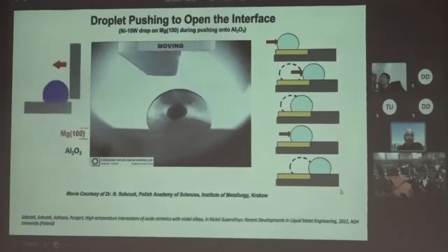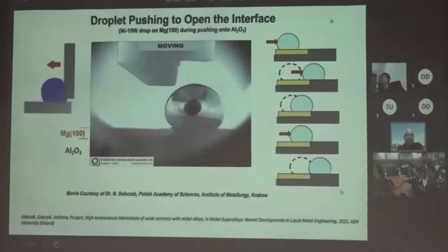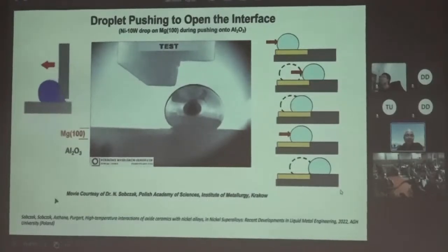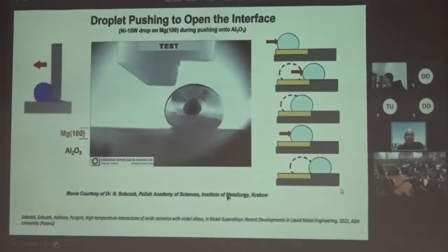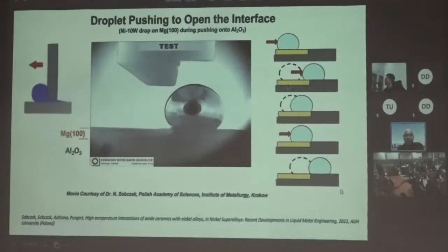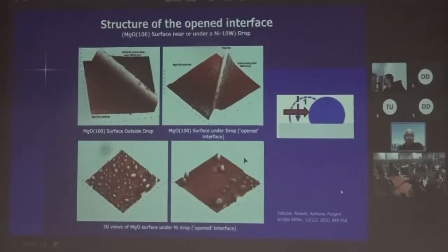One of the things we have been able to do is to push liquid droplets on the surface. So this is actually nickel tungsten on magnesium oxide, not magnesium, but magnesium oxide. And under high vacuum, you are able to push the droplet and open up this interface after a fixed amount of time. And after cooling, you can actually look at the interface and see what kind of reaction occurred. So something interesting we see, after the droplet is pushed out, the little droplet that was 2 to 3 millimeters in diameter breaks up into micron-sized droplets underneath. And those little droplets get captured into these kind of dislocation etch pits, really teeny etch pits. So we are actually looking down from the top on the surface that was cleaned up by pushing the droplet after a fixed amount of time.